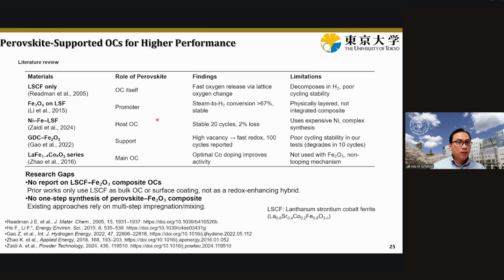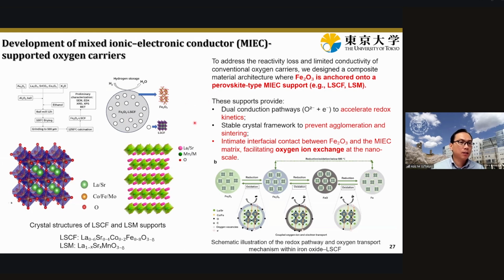So another piece of research concerns not only doping but also mixing with perovskite structures. In this case, we use LSCF, lanthanum strontium cobalt ferrite. What we expect here is how far we can have the mixed ionic-electronic conductor influence. By adopting materials that can facilitate mixed ionic-electronic conduction, we can have much better oxygen ion exchange in this case.